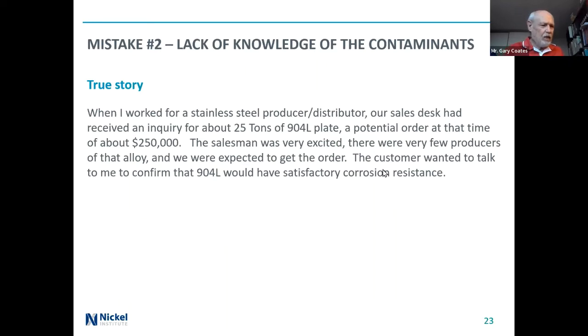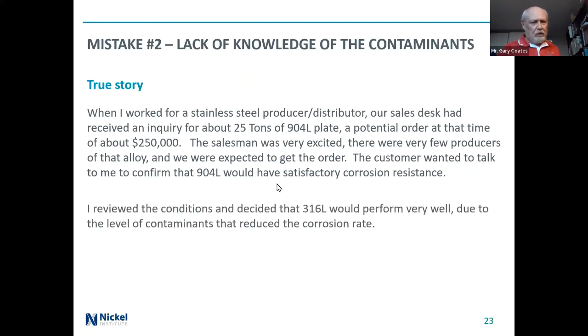So a true story, when I worked with a stainless steel producer, distributor, our sales desk had received an inquiry for about 25 tons of 904L plate. At that time, it was worth almost $250,000. Of course, the salesman was very excited. There were very few producers of the alloy at the time, and we were expected to get the order. But the customer did want to talk to me to confirm that 904L would be satisfactory for that particular service environment.